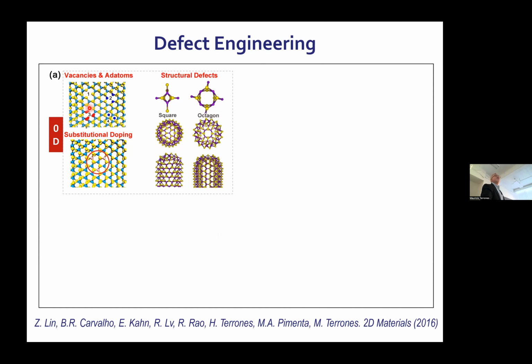So you create a vacancy, you can remove sulfur atoms, or I mean, chalcogen atoms or metal atoms, and you can have substitutional doping. That means replacing the metal, replacing the chalcogen. So you have these sorts of point defects, or you can have these structural defects that are square-like or octagon-like defects that will provide curvature to the system. So it's similar to the pentagons, what they do to graphene. They create curvature and you can create a fullerene. In this case, you could create cages eventually, or you can create some negative curvature with the octagons.